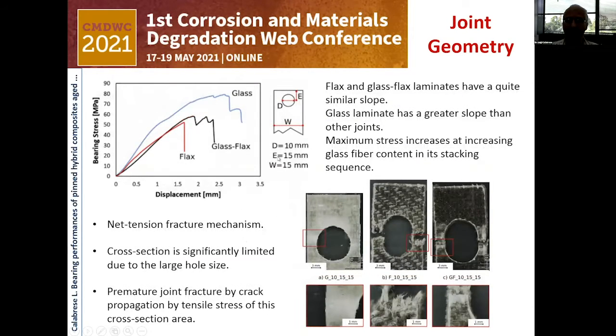Now, considering large edge distance but also large diameter, we have still another mechanical behavior. In this case, the main fracture, for all of them, is the net tension fracture, a premature fracture where the tensile properties of the fibers play a relevant role. In fact, the stacking sequence influences significantly the maximum stress, with obviously the higher behavior for the glass one and intermediate performance with the glass flux.